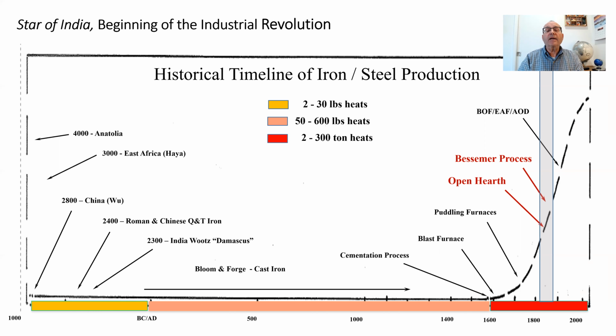And so this was occurring, and they were able to produce a lot of cast iron, but now the real big bottleneck came in refining that cast iron. In other words, refining and reducing and controlling carbon content to make it more ductile and easily forged. And so there were two processes that were competing: puddling furnaces, open hearth processes, and the Bessemer process, which is coming into this. And this was right about the time that the Star of India and a lot of these iron-hulled ships were being produced. And so let's look at these two processes, in particular the open hearth process and the Bessemer process.